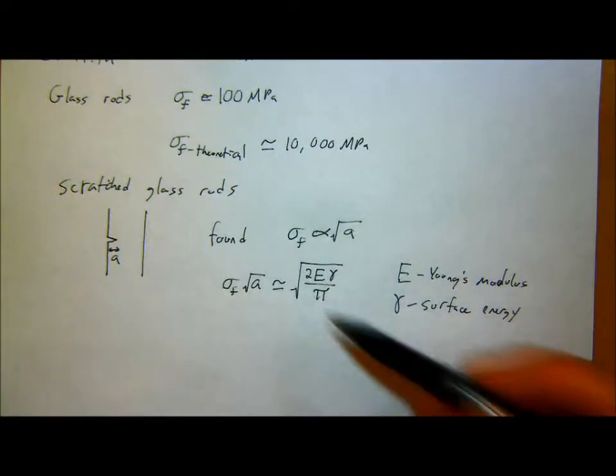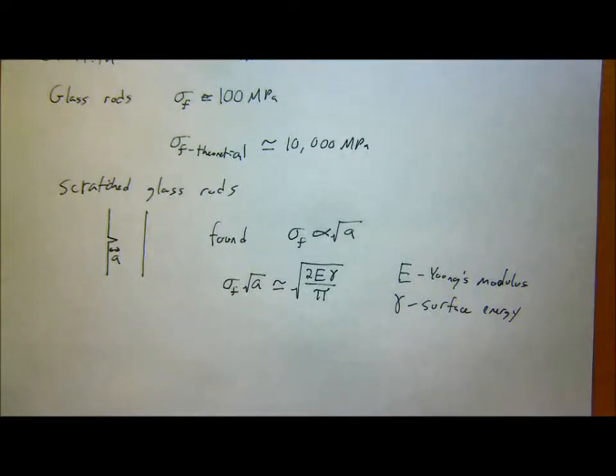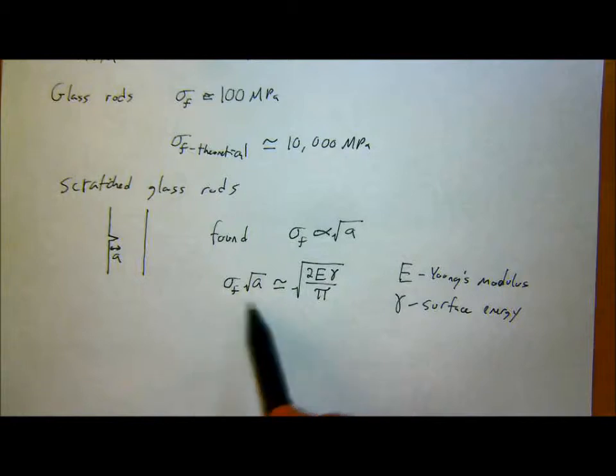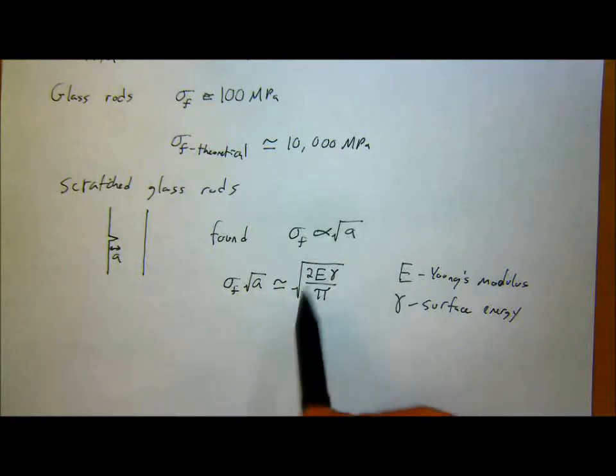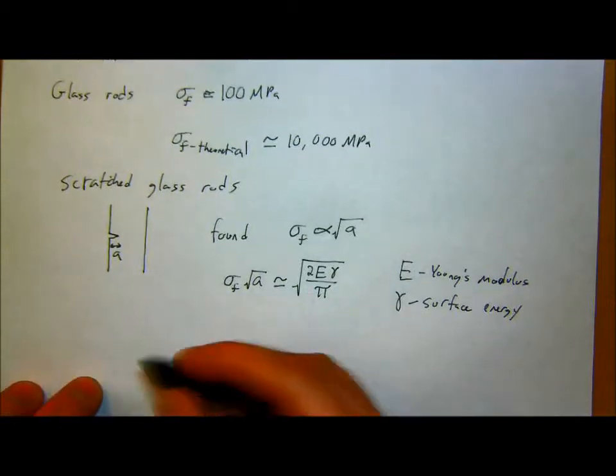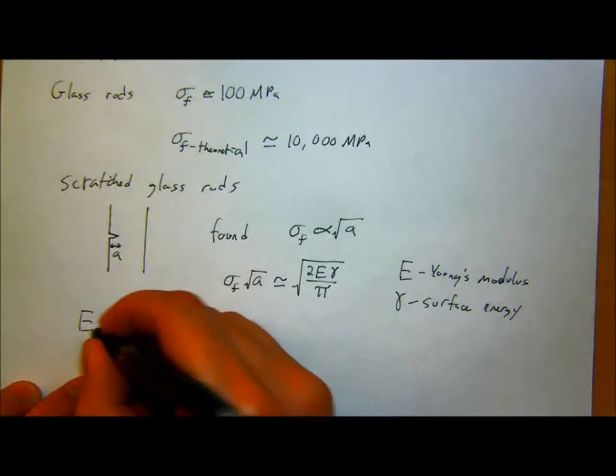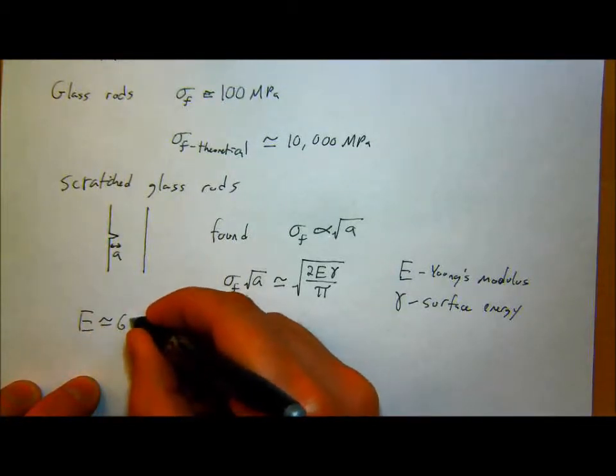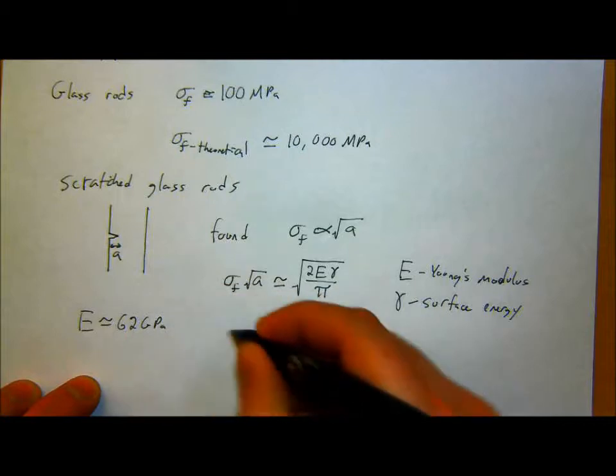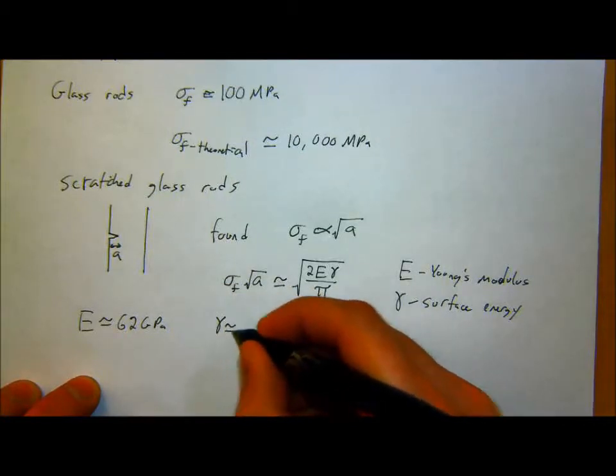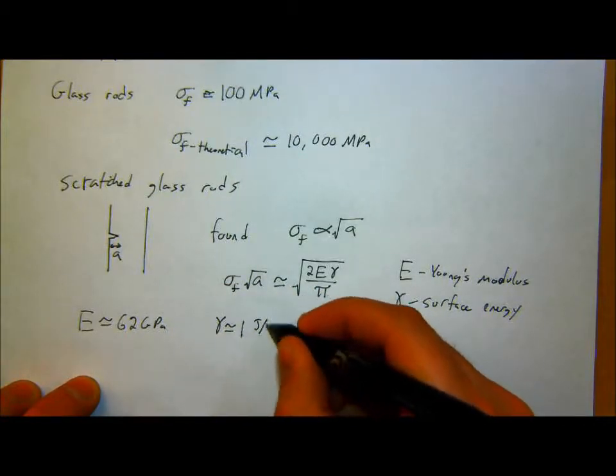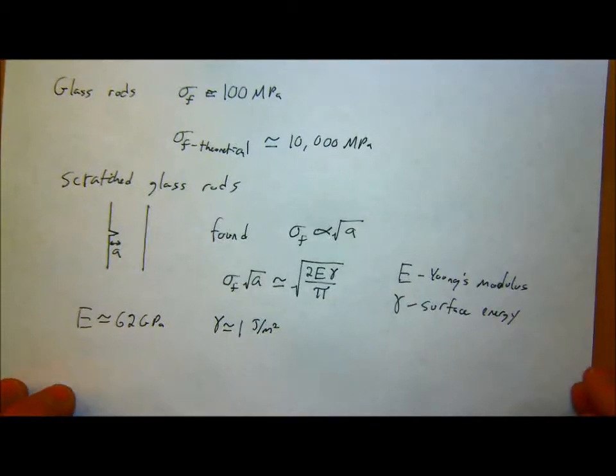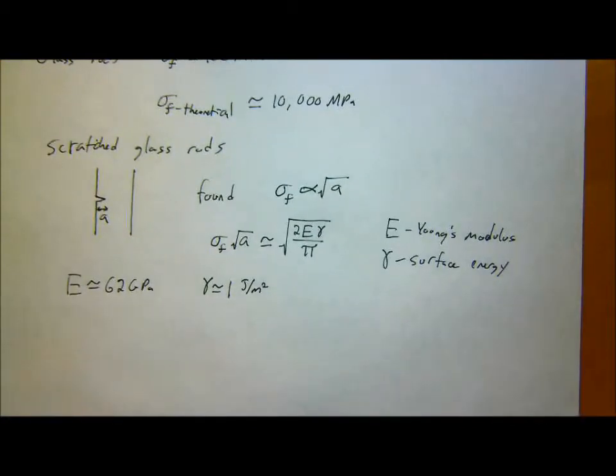And for the glass that he was using, E is about 62 GPa. Surface energy is about, for glass, 1 joule per meter squared. And plugging in these values, he was able to predict pretty well what the fracture strength of glass would be, just using this sort of empirically derived relationship.